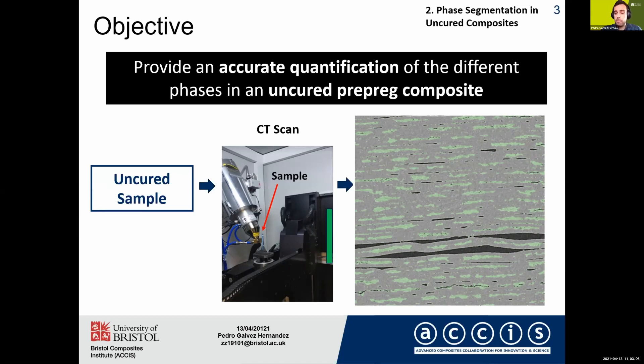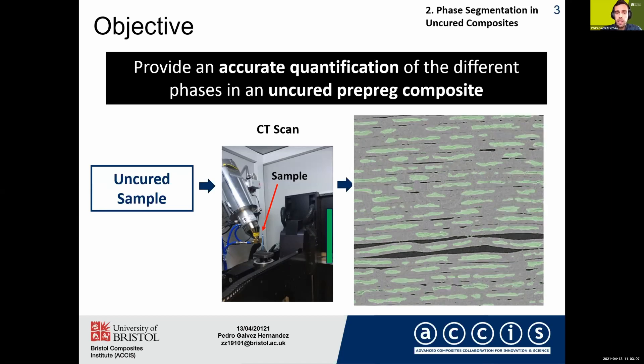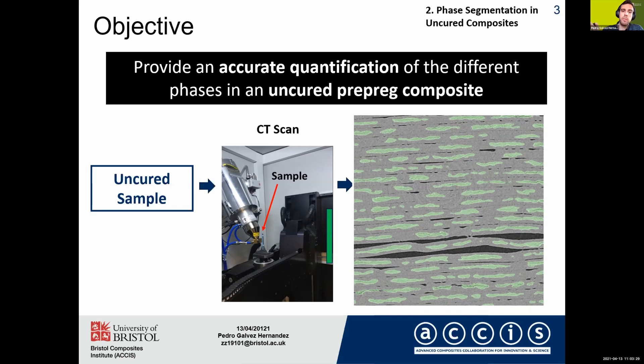I designed and trained a deep learning model to automatically segment the dry areas in this 3D grayscale image. The result of this segmentation using deep learning is much cleaner and much sharper. The false positives and false negatives are greatly reduced, and the accuracy of the representation of the dry areas in the 3D microstructure is highly improved.